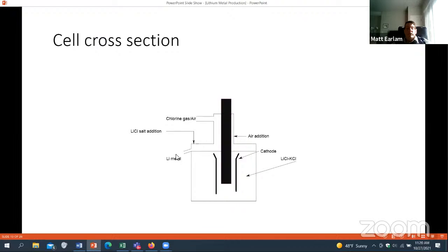Some cells have an overflow similar to a sodium cell. Some cells use a hand ladling situation. They have salt addition. This is manually done by adding salt in powder form to the cell. And then you actually have an air addition that allows you to pull the chlorine-air mixture off at a pretty low concentration of chlorine, somewhere less than 10%. Still deadly to a person, but a lot less damaging to equipment because you've quenched the chlorine considerably by this air addition that you pulled in this way.